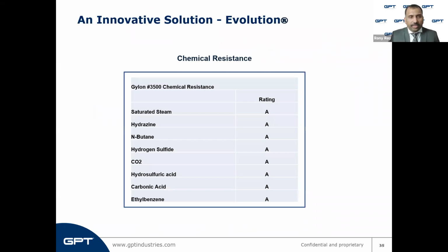Another thing that we did to make sure that the evolution is chemically resistant to many of the conditions that GRE or glass reinforced epoxy G10 and G11 laminates are not, is that we have compared the chemical resistance to many other media conditions. And as you can see, we have introduced saturated steam, hydrazine, N-butane, hydrogen sulfide, carbon dioxide, hydrosulfuric acid, carbonic acid, ethyl benzene, and it gets a very good rating. It's a rating A. That means it is good to be used against these chemicals and will not be chemically attacked. So we made sure that the new solution is chemically compatible where a GRE normally fails.